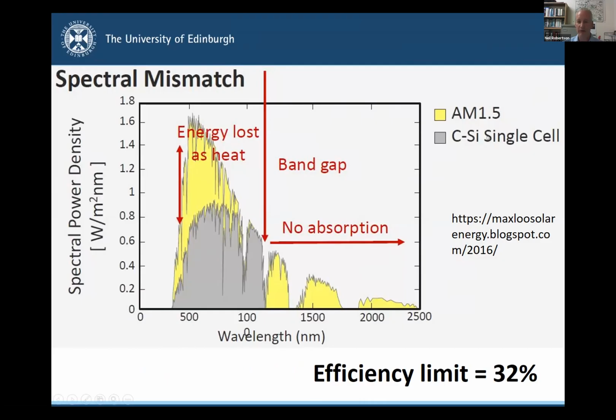absorber solar cell, such as crystalline silicon, has a theoretical efficiency limit of about 32%. So when we talk about silicon reaching 27% best cell efficiency, that's not 27 from a possible 100, that's 27 from a possible 32. So actually incredibly well optimized. And that's because with a single absorber, you can only have one band gap, so you can only optimize for one particular wavelength range. Light of lower energy, this is the solar spectrum, is not absorbed at all, and light of higher energy wastes some of that energy as heat because it has too much energy to be optimized for that absorber.